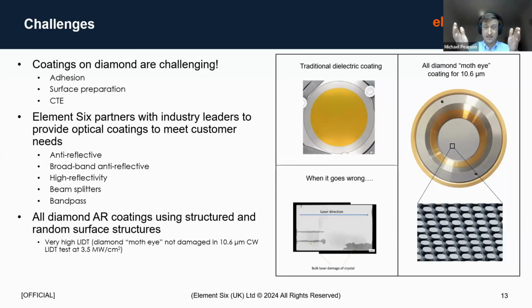see that what's happened in this case is the coating has failed on the left-hand surface. That's caused an absorbing feature on the surface, and then the laser has drilled through the diamond, creating a long extended graphitic hole in the diamond, which is absolutely not what we want. So it's important to get these things right, and when we don't, it can lead to issues such as that.